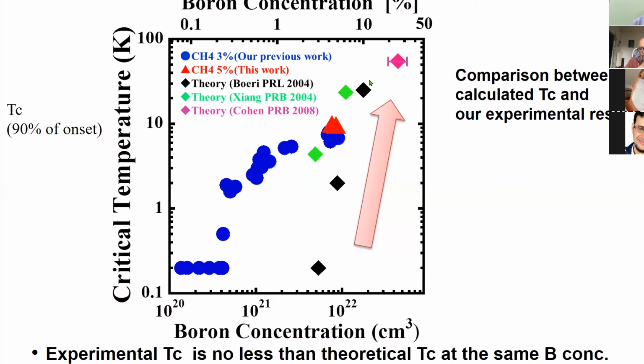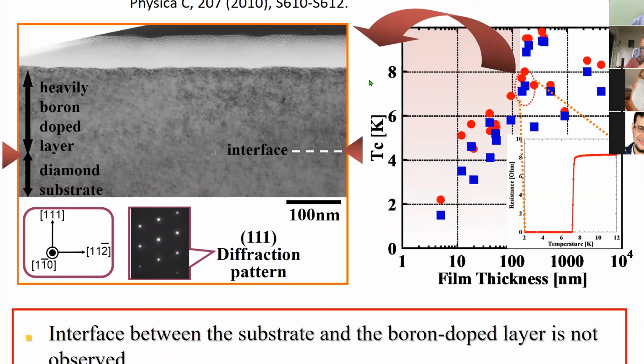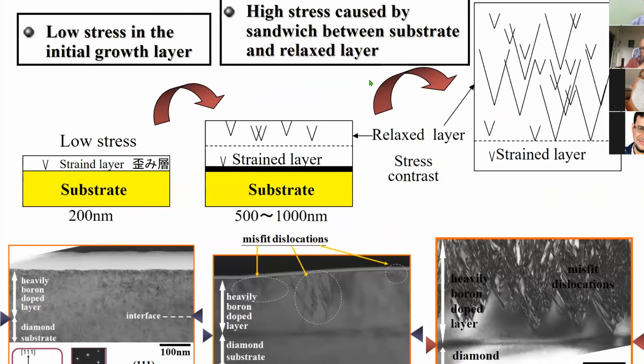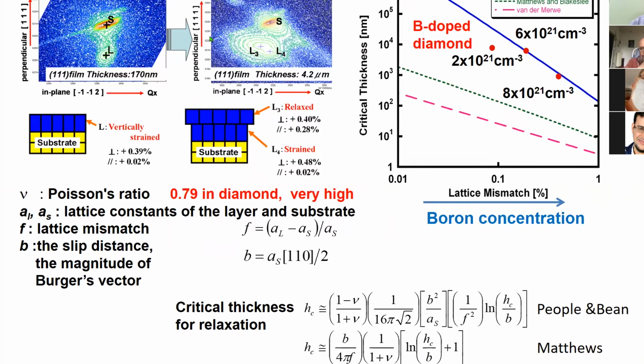And then they showed a very clear tendency. I'm sorry, I don't have this bibliography today, but what we observed is that the diamond is relatively expanded vertically. I think there's data for that. This is a reciprocal mapping of the X-ray, and this is a substrate, and this is a layer film. Reciprocal mapping means a reciprocal lattice measurement, and this is one planar structure. This is vertical. So in the vertical, the reciprocal lattice becomes small. What that means, this is a schematic, easy to understand what's happening. So you can see the lattice expand like that, vertically. Then we get relatively high TC.